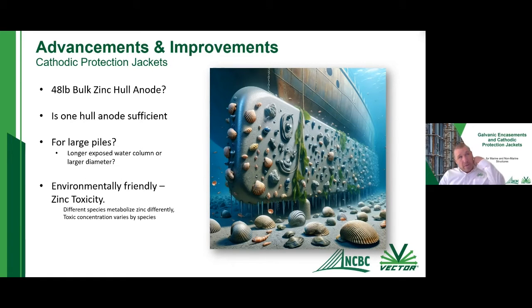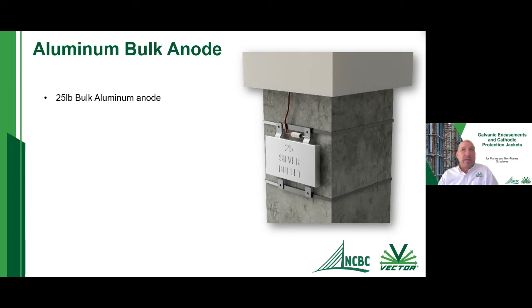So this is some of what had been looked at. Is one hull anode sufficient, as well as for these larger, longer piles? Another thing that is becoming more predominant is zinc toxicity. If you have certain estuaries or ports with a lot of marine environment, zinc toxicity is becoming a concern, and aluminum is a much more environmentally friendly alternative to zinc. So what ended up happening was that a 25-pound bulk aluminum anode was specifically designed for pile jackets. It was a custom design, shape and size, and it fits the majority, about 90%, of the piles that actually receive cathodic protection out there.